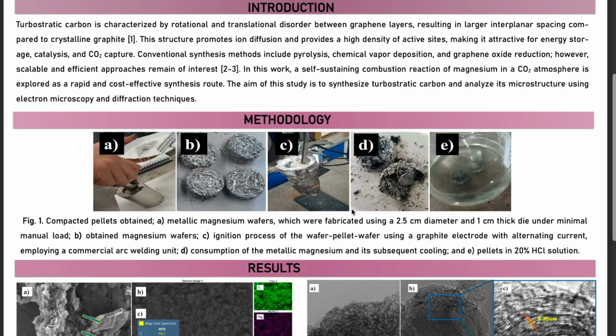The self-propagating combustion reaction rapidly reduces CO2 into elemental carbon within seconds. In panel D, we observe the complete consumption and cooling of the metallic magnesium. Finally, in panel E, we purify the product by immersing the resulting pellets in a 20% hydrochloric acid solution to leach out remaining magnesium oxide impurities.